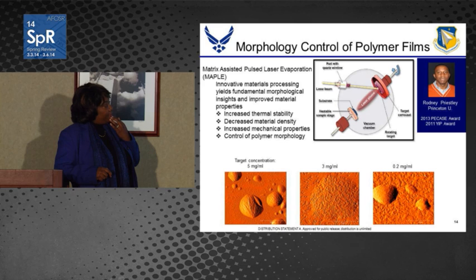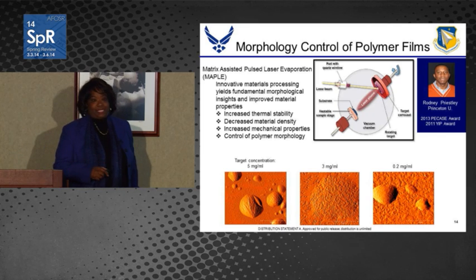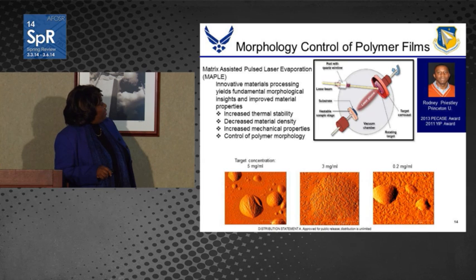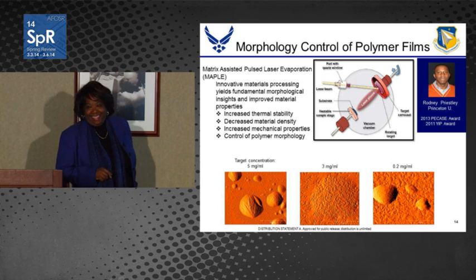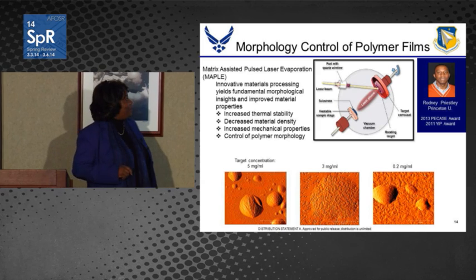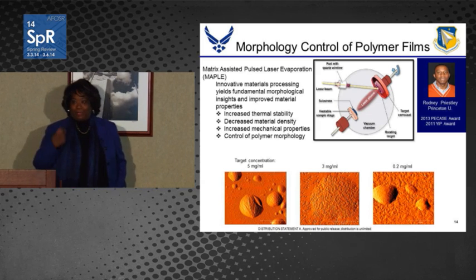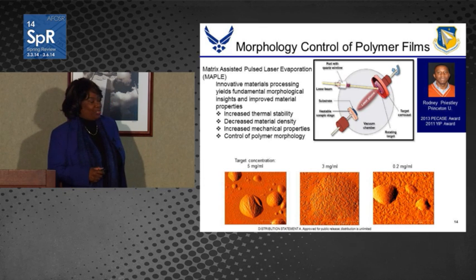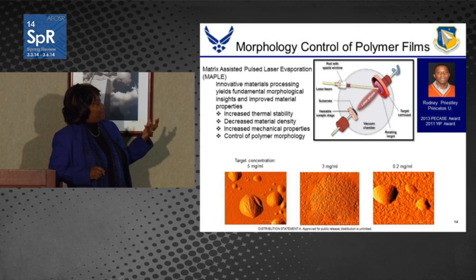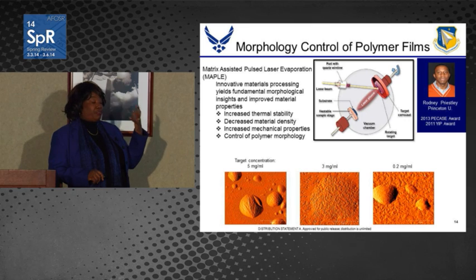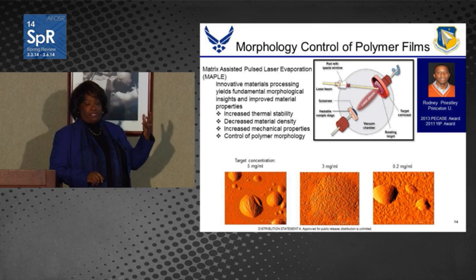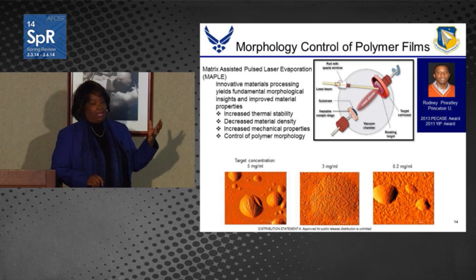Dr. Priestley was a YIP winner, a recipient for my program in 2011, and I was very happy to see that he won the Presidential Early Career Award this past year. And so what he's doing at Princeton is employing a matrix-assisted pulsed laser evaporation system. Did I say maple? I meant matrix-assisted. The acronym for all of that is called MAPLE. And MAPLE is a process that's analogous to pulsed laser deposition, except that in pulsed laser deposition you have a solid target. Here in MAPLE, the target is a frozen solution of a dilute polymer in a highly volatile solvent.